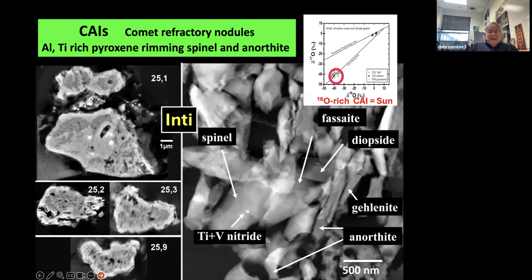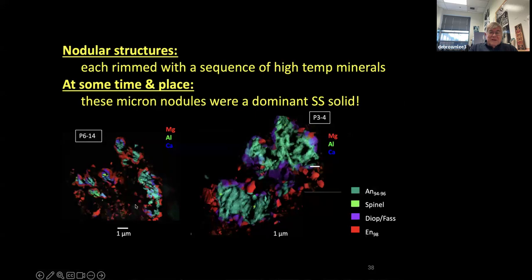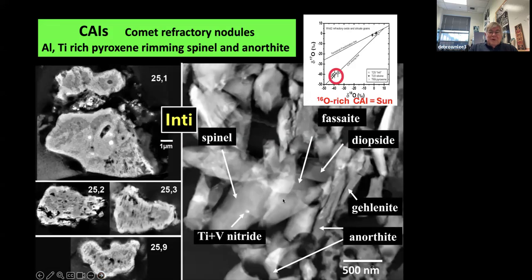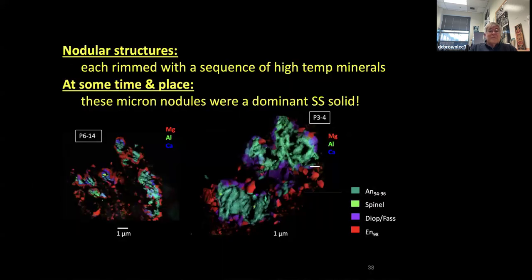We found these classic CAI materials: spinel, fassaite, grossmanite, gehlenite, and anorthite, and some things that were a little surprising, like titanium vanadium nitride, which I'll show more pictures of shortly.